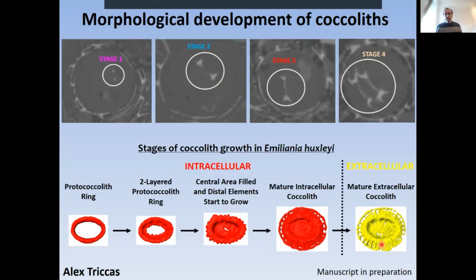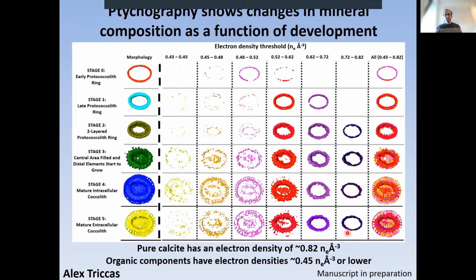This is all very interesting and very exciting that we can pinpoint these stages, but there's more that we can extract. I mentioned that what is really exciting about ptychography is that it's quantitative. So we can get an electron density value that we can directly correlate to the composition of the material that we're looking at. And we can do the segmentation, the computer reconstruction, based on the electron density that we see in the coccolith. Just to give you a reference, the coccoliths are made of calcium carbonate in the form of calcite. The electron density that we expect for pure calcite, and this is both calculated and roughly what is observed in materials like mollusk shells, which are also made of calcite, is about 0.82 electrons per cubic angstrom.